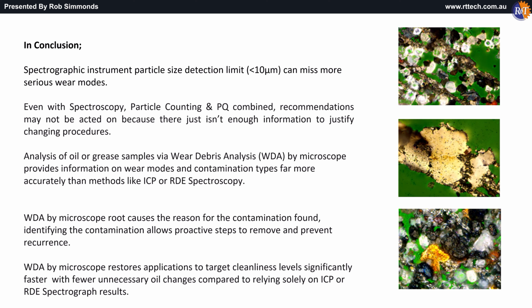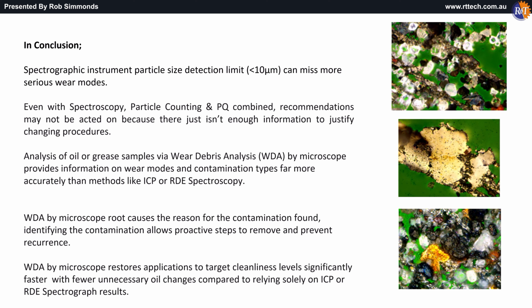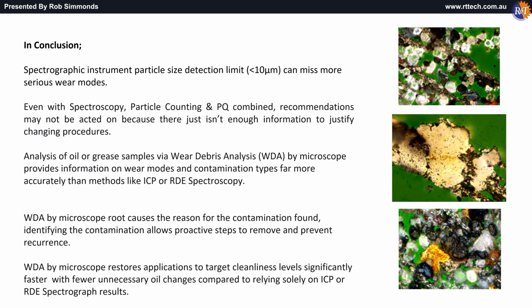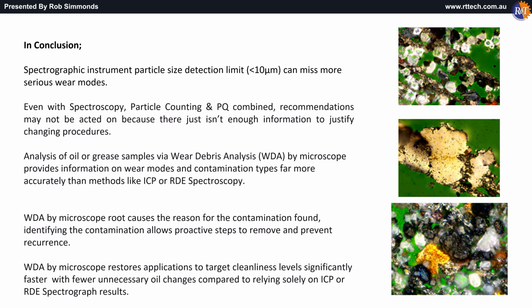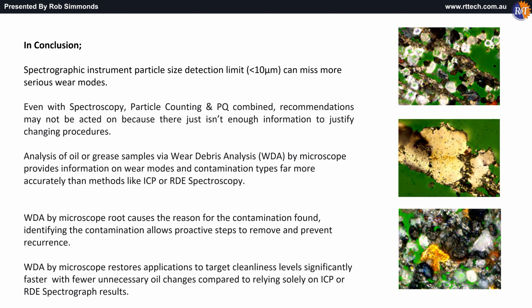Note the three images on the right. Note how the microscope has root caused the haul truck centrifuge cake sample. The top image displays silica crystals. The engine has been dusted. The middle image is the large chunks of white metal embedment layer the silica crystals are abrading from the bearings. The bottom image displays the fine dirt causing arcing in the engine's bearings, producing these carbonized lubricant particles found in the sample. From the information gained from the microscope work on the centrifuge cake, the recommendation to the equipment owner is to work on seeing if the air filtration can be improved.